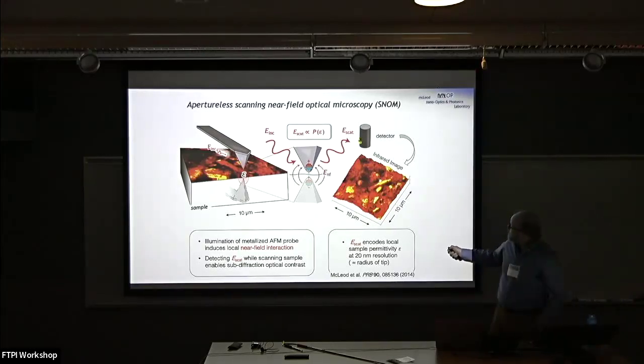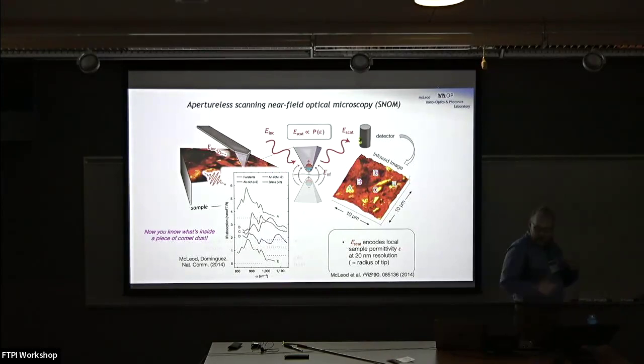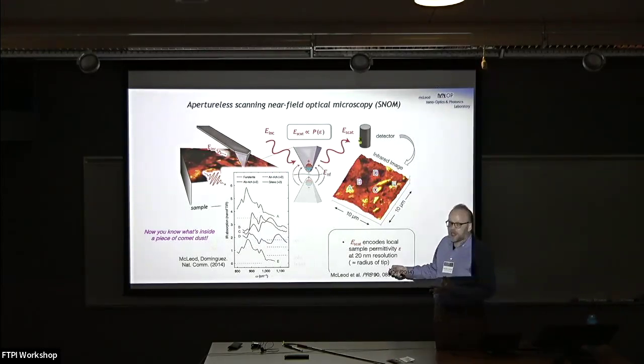And I should say, to go in the converse direction, I have this lovely map, but what I want to do is extract quantitatively the optical conductivity and permittivity. Well, that's obviously a little bit more challenging. That's an inverse scattering problem. But I'll let you in on a secret, we have fast computers and we solved that problem some years ago. Anyway, spectroscopy. If we go in and illuminate at a variety of different energies, we can record a spectrum.